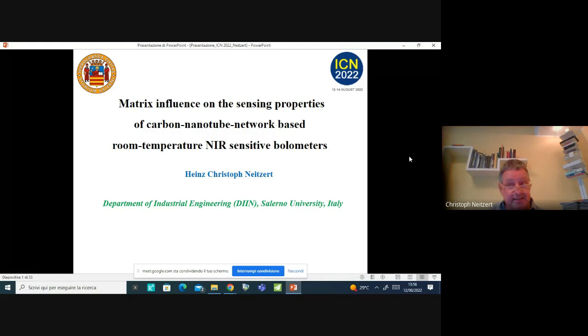But as I told you, we stayed more with carbon nanotubes. We touched graphene more for battery operation. And of course, graphene is ideal for what I showed you, the nanotube network for the solar cells. That's my field actually, photovoltaics, my original field. So you can do this even better with graphene, with large graphene sheets, which you put just on top of the solar cell.